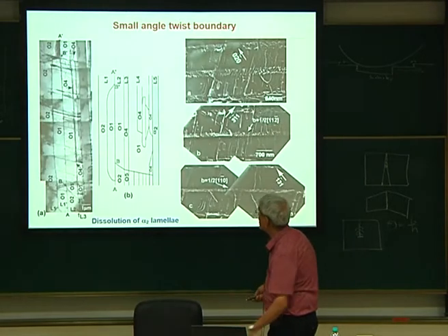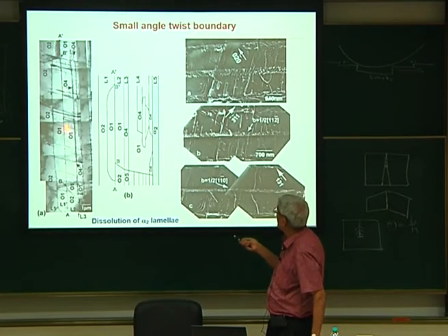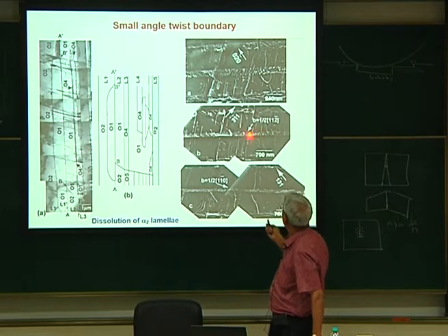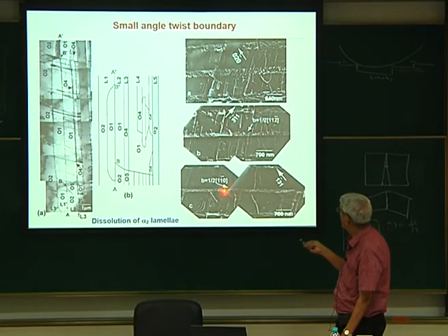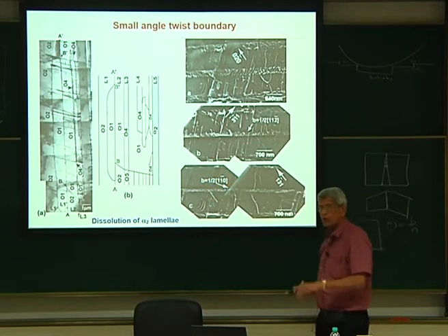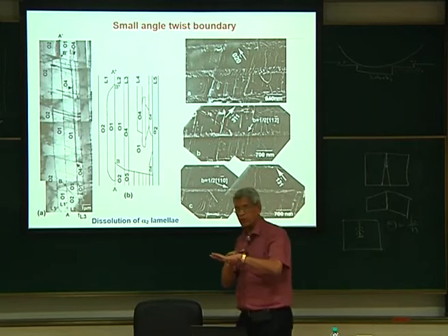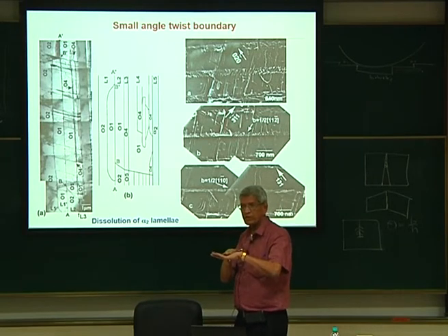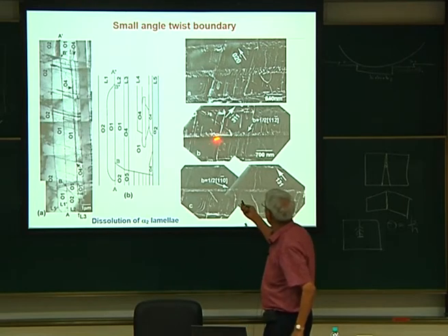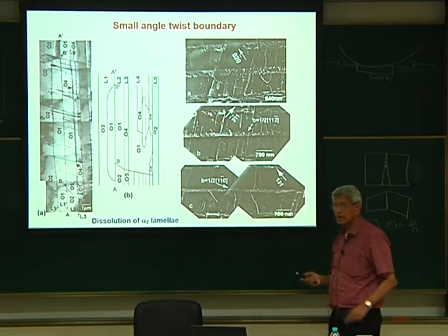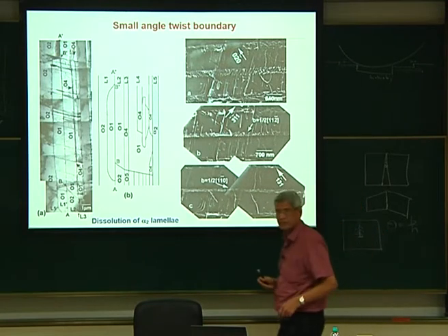These dislocations have also been analyzed, and it has been seen that in this particular one the dislocations are 1/2<112̄>, and in this particular case it is 1/2<11̄0>. These Burgers vectors are perpendicular to each other. This sort of dislocation is the one which is balancing the other. With this network, we can have a twist boundary which forms in this alloy system.